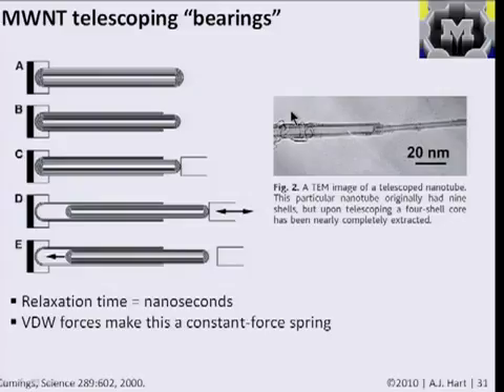And another case in which this has been utilized or studied is in the case of having multi-walled tubes, where you can pull the center of the tube outside of the rest of the tube. And this is sometimes what's called a sword in sheath device. And they just used a manipulator inside a TEM to grab the end of a tube. And they also use the electron beam to kind of cut off the outer walls to blow them away.